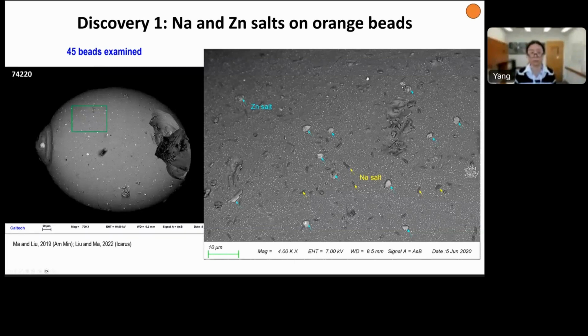One type is a zinc-rich salt, and they occur in a triangular shape, suggesting a trigonal crystal structure. We have also seen darker rods that are enriched in sodium. The distribution of those two phases is quite widespread. This is an example of a bead. If you look at the left-hand side, we have the zinc-rich phase in quite a high number density on the surface of this bead, and there is a cluster over here as well.